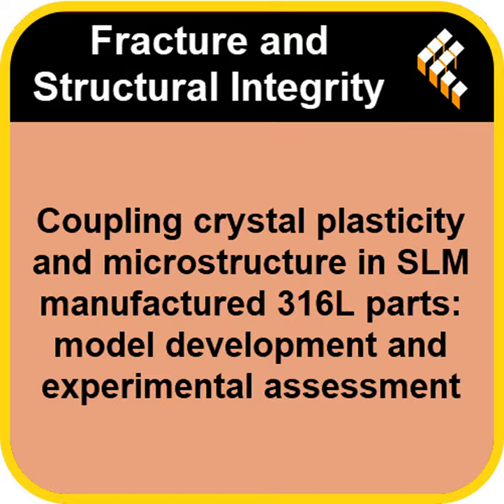First, they confirmed the classic Hall-Petch idea. If you change the grain size from, say, 110 microns to 130 microns, the yield stress changes by about 1.3 to 1.8%. Okay, so a small expected change there. But what about that 190 MPa of residual stress? Okay. The conventional wisdom is that those locked-in forces are the dominant factor. What did the model show? This is the shocking part.